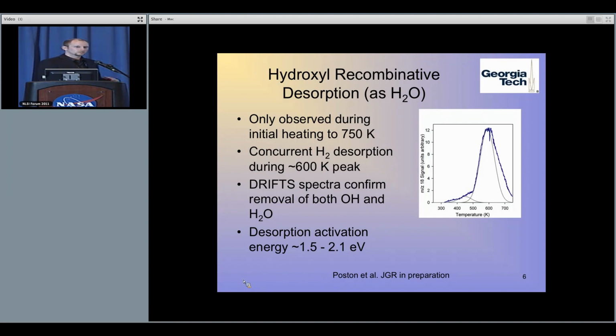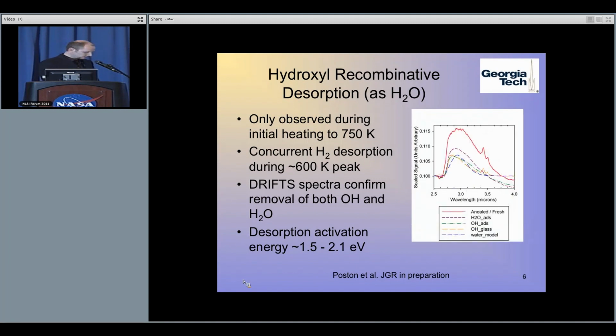So we actually quickly pulled the powder out of the chamber, stuck it in a DRIFTS infrared apparatus, and measured the difference between the signal near the 3 micron range from the annealed powder and ratioed that to a powder that we hadn't annealed. The red line is the difference between the two, and hopefully you can see that it does not match water alone.